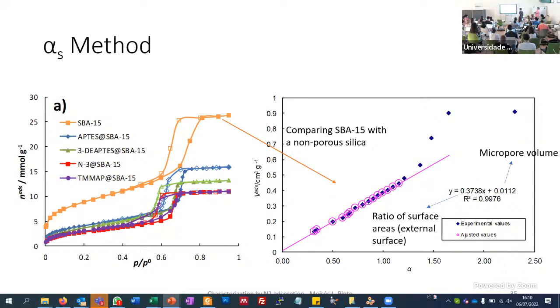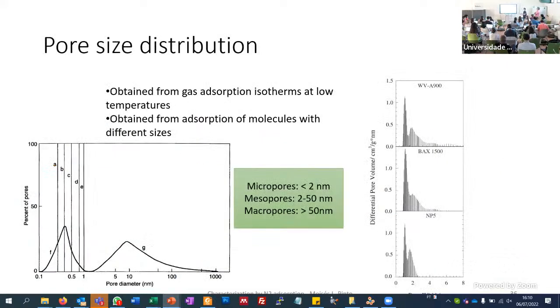So we can also calculate pore size distributions. We are not, of course, going to do this in here, but just to remember that micropores are below 2 nanometers, mesopores we call them when they are between 2 and 50, and macropores when they are above 50 nanometers. Sometimes people talk about mesopores without understanding that all of these pores are actually on the nanoscale. And we can also plot the pore size as a function of volume.